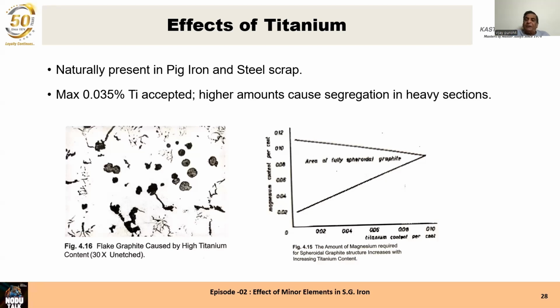Titanium is one of the most dangerous elements that can be present in raw materials. It is naturally present in pig iron, especially Indian pig irons, because along with the iron ore, there is titanium ore present in the raw iron ore used for making pig iron and steel scrap. A maximum level of titanium of 0.035 is accepted. But look at its effect on the graphite structure. Figure 4.16, flake graphite caused by high titanium. As the titanium content increases, look at the figure on the right.